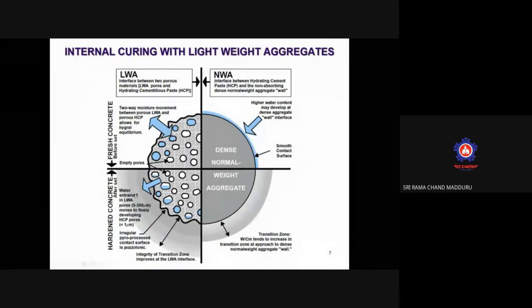In the case of hardened concrete also, the same thing can be observed. Surrounding the aggregate, you can see here a dense interfacial transition zone with the help of lightweight aggregates. Whereas in the case of normal aggregates, this type of mechanism is not observed; only water accumulation is observed. As you know, natural aggregates are very dense, no pores are present, and the water is accumulated only on the surface. So that is the advantage of lightweight aggregates. They absorb the higher amount of moisture, and if water is required for the hydrated cement paste, they will release the water content.